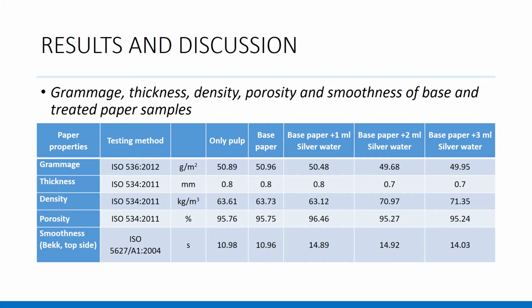During this additional drying process, the effect of the temperature and the pressure on the machine has the effect of calendering effect on the paper, which is also confirmed by the data on the density and porosity indicators of the investigated papers. From the data in the table, it can be seen also that as the amount of silver water increases from 1 to 3 milliliters, the density increases and the porosity decreases.